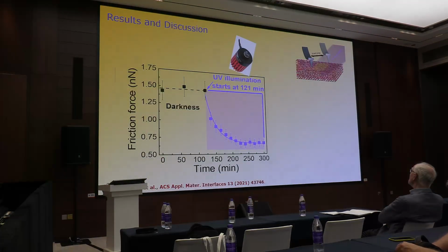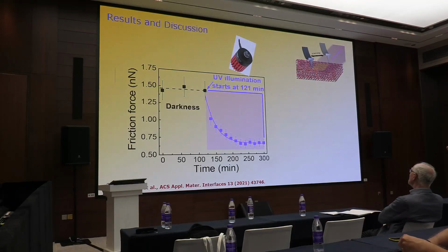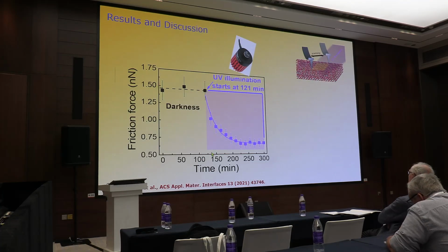Well, from here to the end, we use the silicon nitride tip. We remove the silicon tip and only use the silicon nitride tip in our AFM experiment. You can see the friction force is in the scale of hours, not minutes: 1 hour, 2 hours, 3 hours.